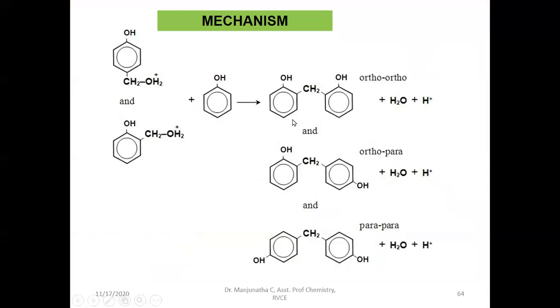Before going to the next case, let me briefly discuss the mechanism. In acidic medium — because we take phenol in excess, it will be acidic — the methylol phenol forms OH2+ (a protonated water / protonium ion). An H+ from the acidic medium protonates the hydroxyl group to give OH2+, and the bond breaks heterolytically. The two electrons shift to oxygen, forming water, and CH2 forms a carbocation (CH2+). This carbocation forms a bond with the negatively charged ortho or para carbon of phenol, due to the electron-donating group. This is how the methylene linkage forms in novolac under acidic conditions.